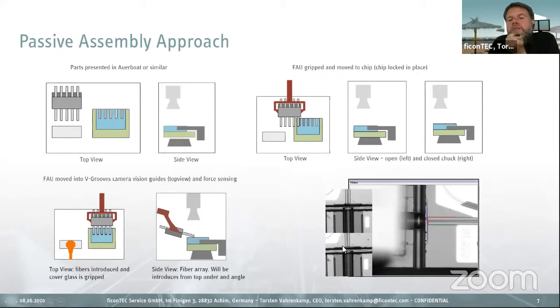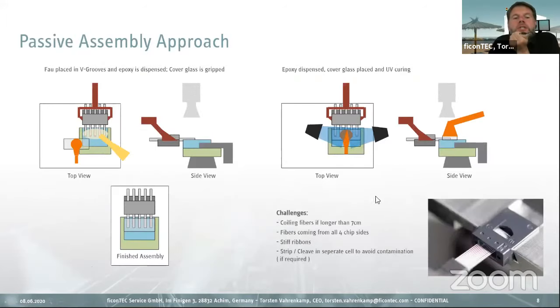And then, if you don't want the fiber touching the front side of the silicon chip, you need to monitor the gap. That is actually what's happening here. And this gap needs to be defined very precisely. Once the fiber has gently entered the V-groove, you put the cover glass down. After you have the epoxy placed here, you bring the cover glass and press it down with a pretty high force.